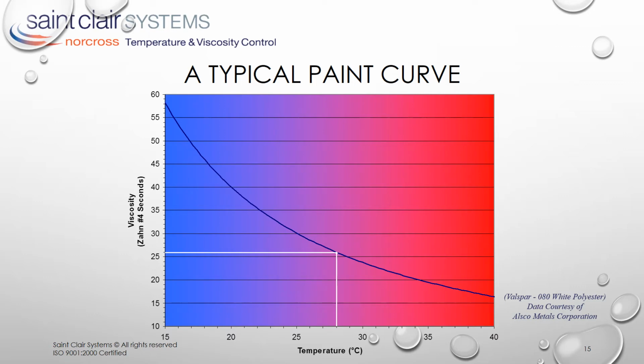But how often does that happen? Right, almost never. So they give us a tolerance of plus or minus 2 seconds. Again, if we extend this over to the curve and down, we can see that this corresponds to a 3 degrees C temperature range from 26.5 degrees C to 29.5 degrees C. So long as we stay within this relatively narrow temperature window, it's about 80 to 85 degrees Fahrenheit, we should be okay. But what most people don't realize is that this varies from formulation to formulation.